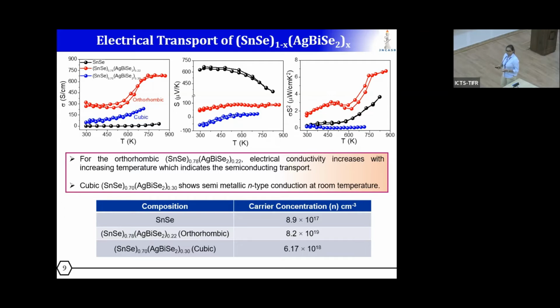And one interesting fact that we have observed is that this cubic AgBiSe2 alloyed sample shows a negative Seebeck coefficient at room temperature, which again tells that electrons are the majority carrier in the system. So by combining these two results, we have got a good power factor of around 7.5 microwatt per centimeter Kelvin square for this orthorhombic AgBiSe2 alloyed system.